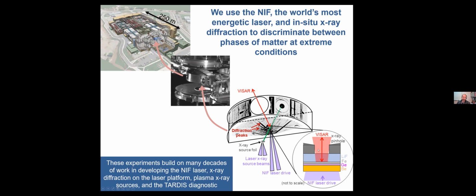That sample package is put on an X-ray pinhole to collimate the X-rays, where the X-rays are sourced by a plasma source. So we use another 24 beams of this laser to generate a plasma from either germanium or zirconium, depending upon the X-ray energy that we'd like. And then when we pulse those X-rays at our samples at peak pressure, we can collect the diffracted X-ray beams on the image plates. And this is how we are able to distinguish and discriminate between phases.